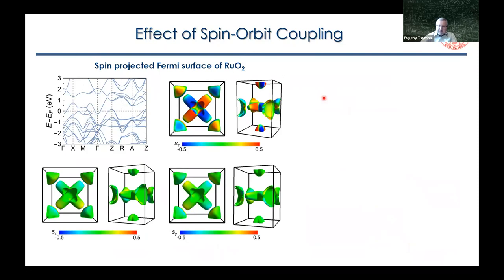And all the effects we've been discussing so far are driven by crystal symmetry and exchange splitting of these antiferromagnets. So if you now take into account spin orbit coupling and calculate the Fermi surface of ruthenium oxide, obviously the shape remains nearly the same because spin orbit coupling is not really substantial. There are some small differences, but not essential.